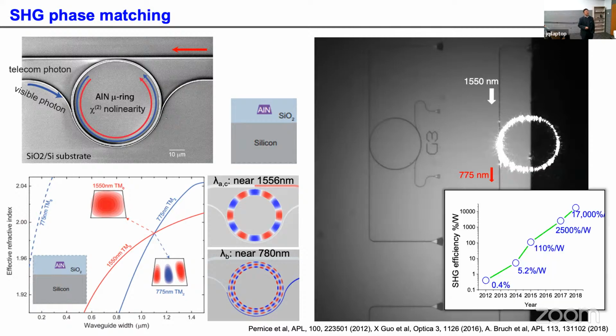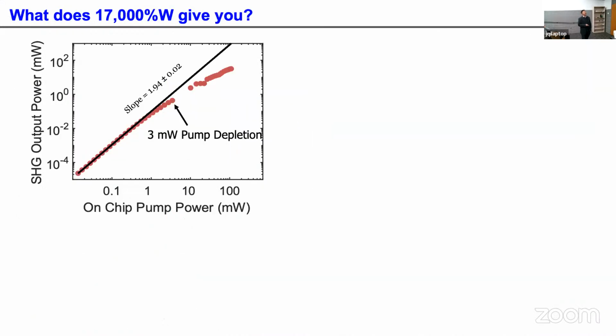So the second harmonic efficiency we normally represent by percent per watt because it is a second-order optical nonlinearity. With the polycrystalline nitride, we can get 2,500% per watt conversion efficiency. With single crystal material, we can get a 17,000% per watt kind of efficiency. So we are kind of obsessed with the number, because the higher the number, the higher the conversion efficiency you can achieve.